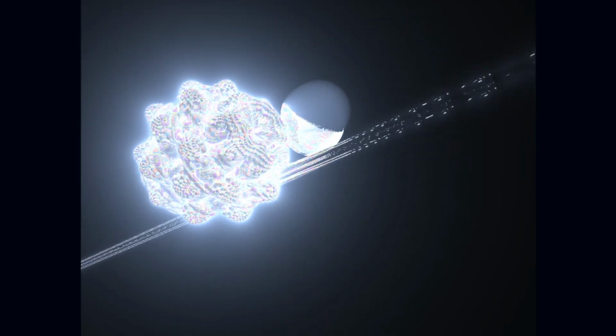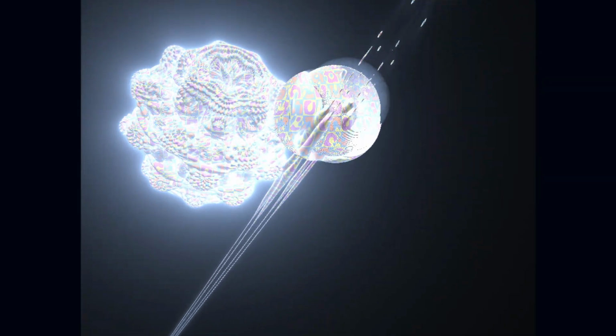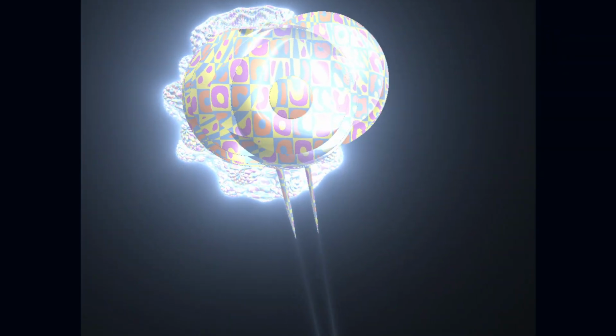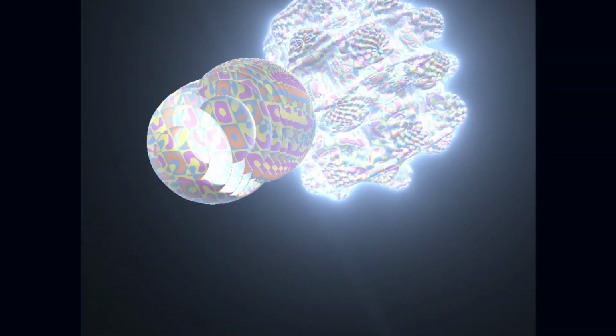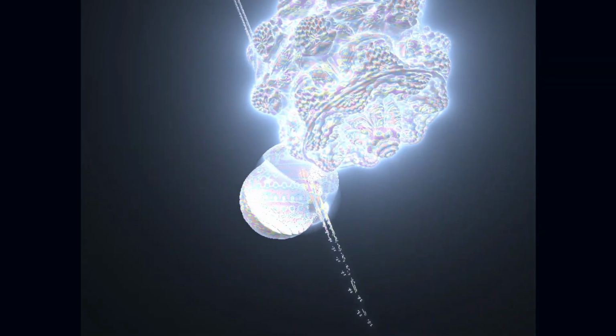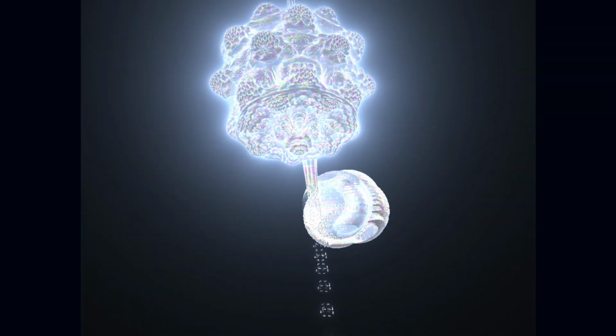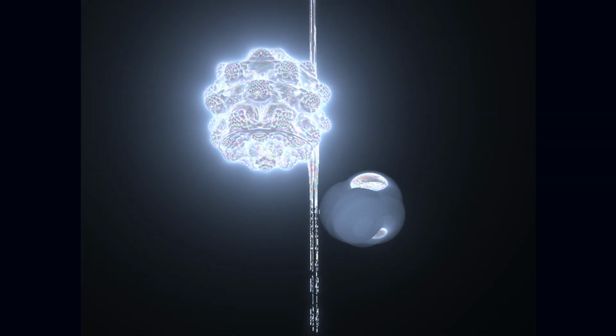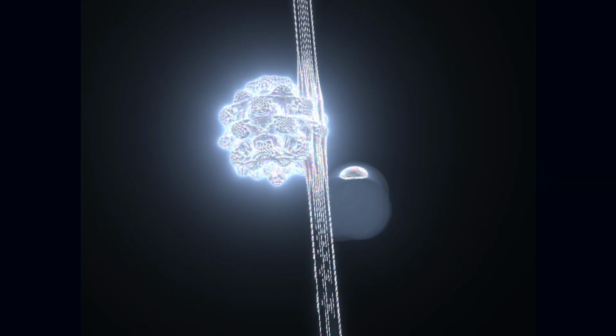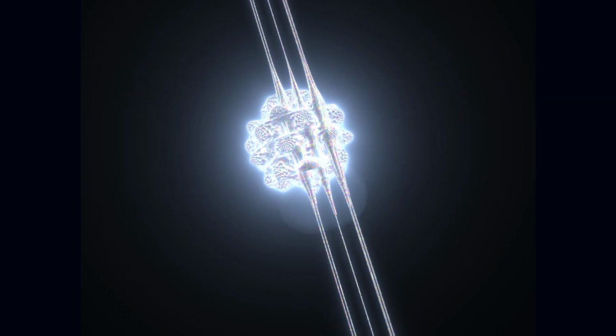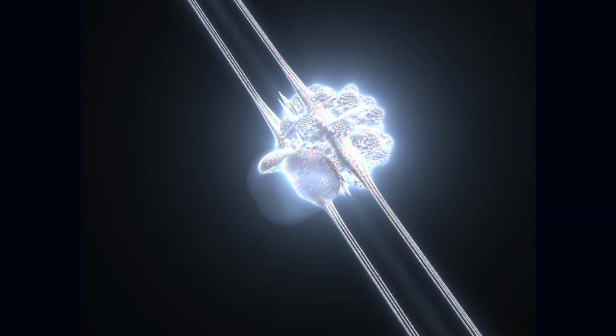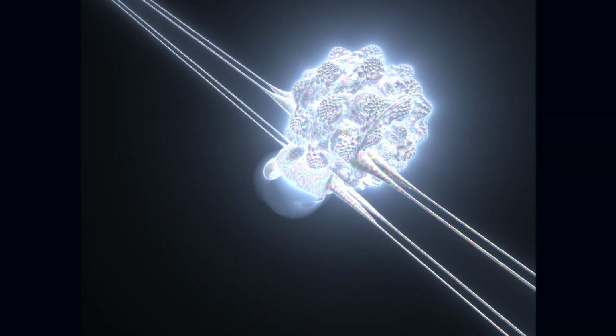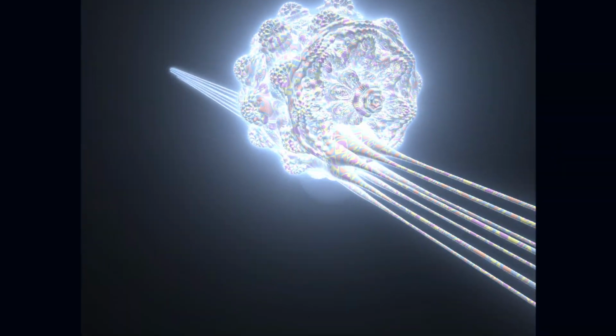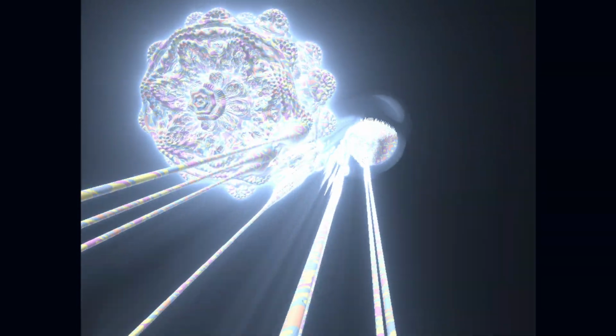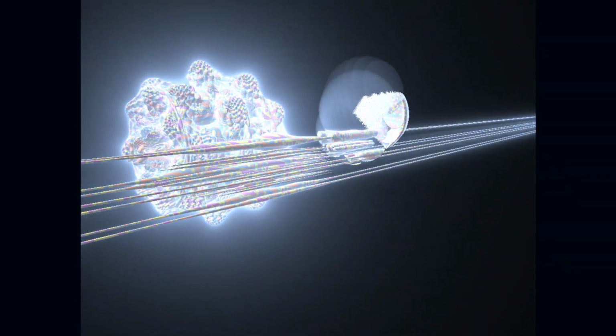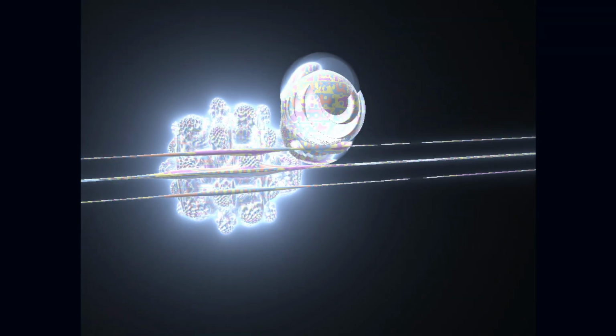The very interaction that makes polarons heavy and causes electrical resistance in the normal state is also the essential pairing mechanism that enables perfect dissipationless current flow below a critical temperature. It's truly one of the most beautiful and counterintuitive aspects of condensed matter physics. It really is a paradox. Electron-phonon coupling is simultaneously the source of resistance for individual charge carriers and the origin of perfect conductivity for paired carriers. How can that be?